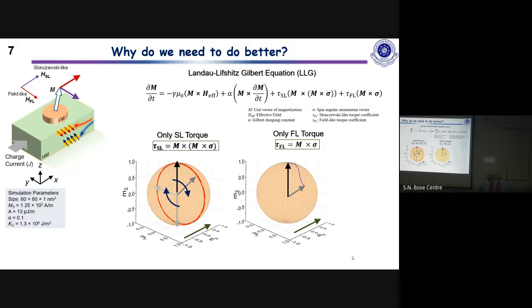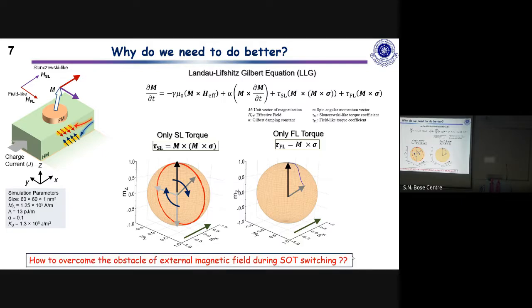So when we are switching from up to down, in that case, that deterministic reversal cannot be obtained only with these torques. When we apply an in-plane magnetic field, the magnetic field actually breaks the rotational symmetry of this torque, and then you have the deterministic switch. So that is the reason why you need this external magnetic field to have a deterministic magnetization. But the problem is how to overcome the obstacle of this external magnetic field during the spin-orbit torque switching.